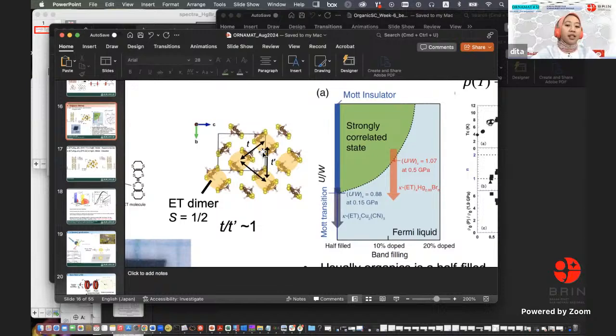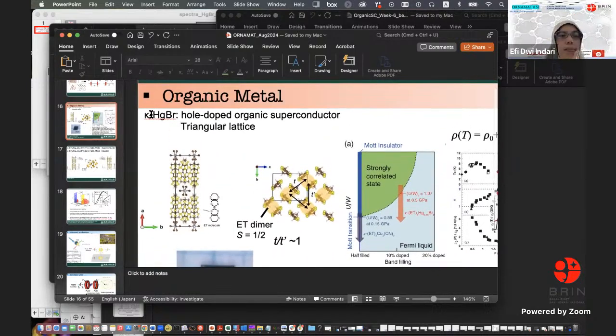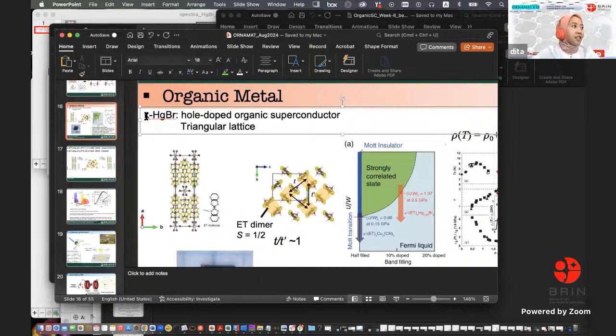So we have several types. Here is kappa, but we have lambda, theta, and others. It's determined by the arrangement of the molecules in the conducting plane. It's one of the advantages of organic. And maybe you think that it will be somewhat unstable. That is also a good point. That's why we need to do the measurement with slow cooling, from high temperatures, in order to avoid randomly ordered ethylene groups. So we have the ethylene group here, the CH molecule. So we need to cool down slowly from 300 Kelvin. That's very typical.